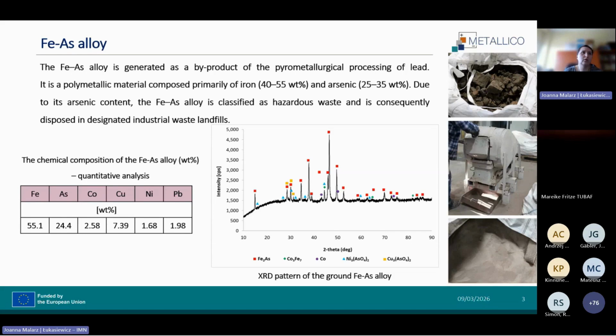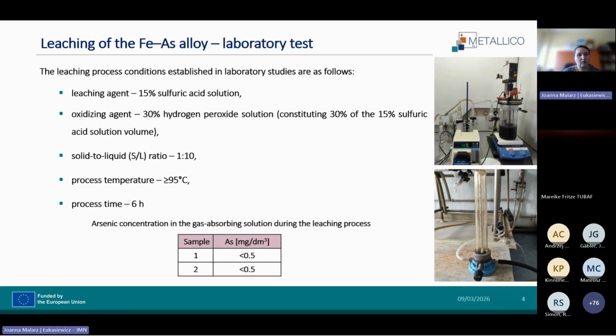The alloy used in our research contained about 55% iron and 24% arsenic, as well as around 7% copper, 2.6% cobalt, and less than 2% nickel. The main components of the alloy occur in metallic form. Because the material contains arsenic, the laboratory scale leaching experiments also included monitoring of arsenic concentration during the process.